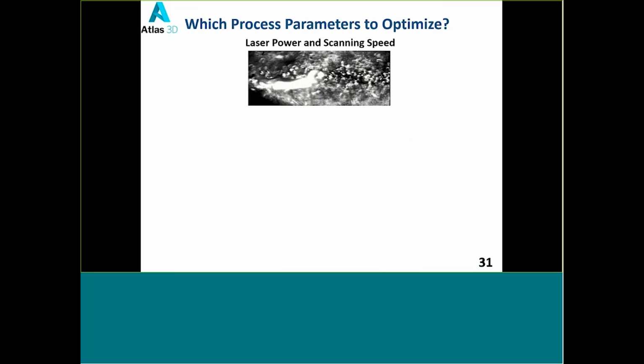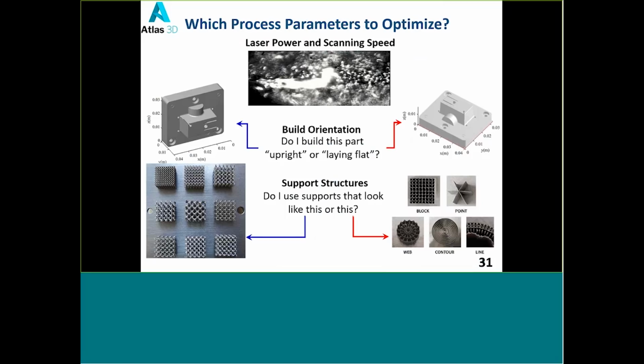So let's talk about optimization. What parameters can we optimize? The first thing that comes to mind is the laser power and the scanning speed. Usually, most engineers just use the default values of laser power and scanning speed in the machine, and we don't need to change them very often. The other two parameters we need to change for every build are the build orientation and the support structure.